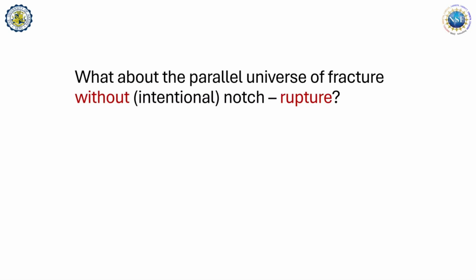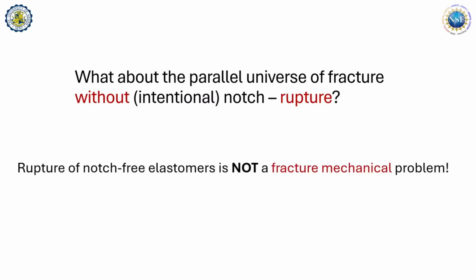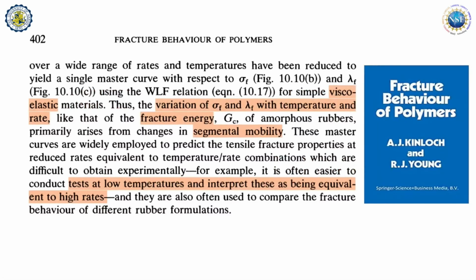That's when you have a cut. The other parallel universe is when you don't have a cut. When you don't have a cut, I think all of my colleagues will today agree with me, when your elastomers are fairly stretchable, we need not worry about flaws. They are flaw resistant or flaw tolerant. In that case, of course, that rupture of your unnotched sample is not a fracture mechanical problem. It is a polymer physics problem. In fact, contrary to what I just said, the textbook suggests that this uncut is the same as the cut. It's the same physics because in both cases, the rate and temperature effect are similar.